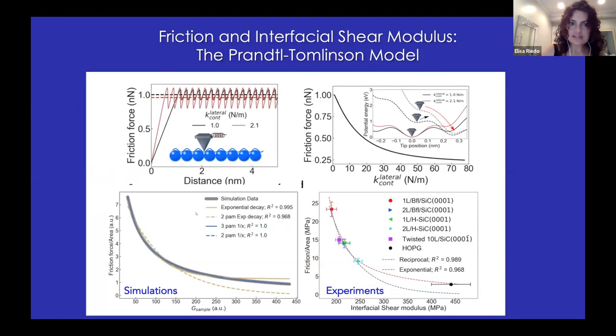Okay, wonderful. So this is the model. This is the familiar Tomlinson model. By running a very simple simulation of the Tomlinson model and plotting the friction as a function of the interfacial shear modulus, as you can see here, we get a very similar result to what we obtained from our experiment. And we even get the same type of fitting function, which is a simple reciprocal function, which, as you can see here, works better than an exponential decay.